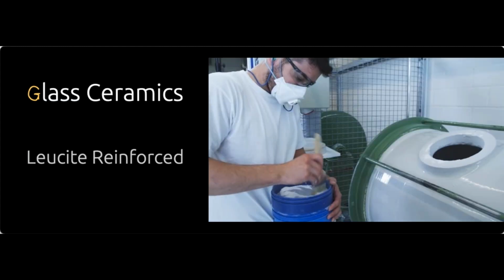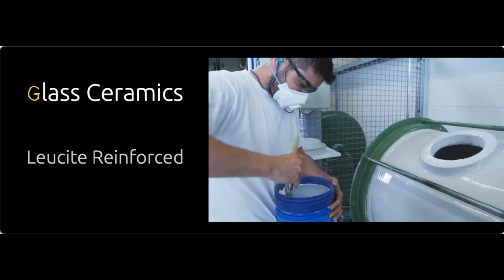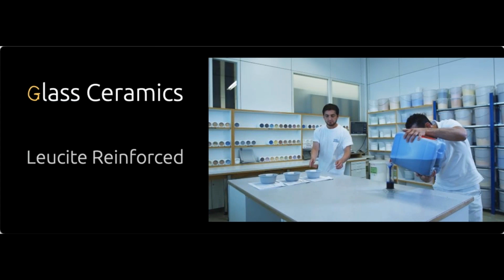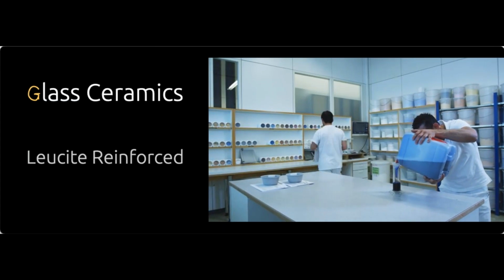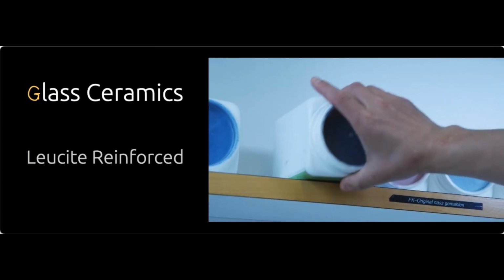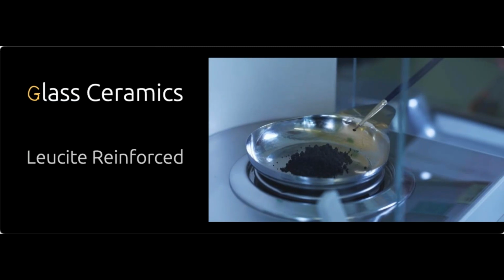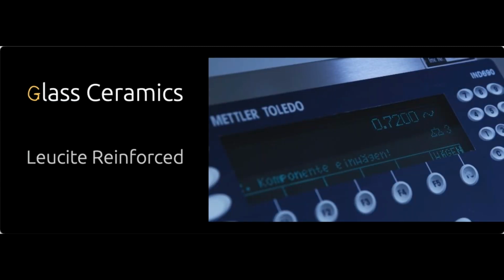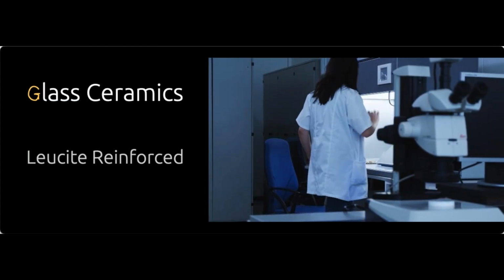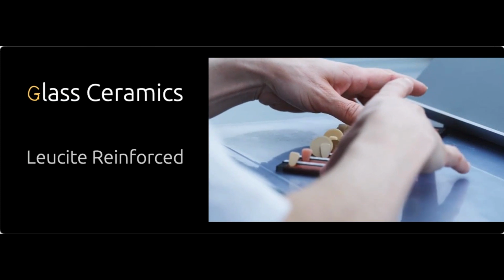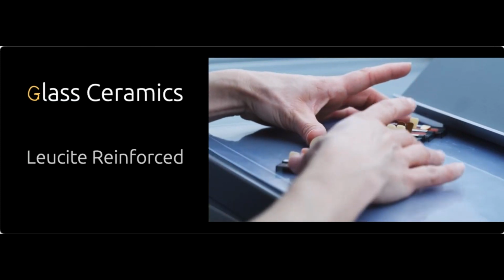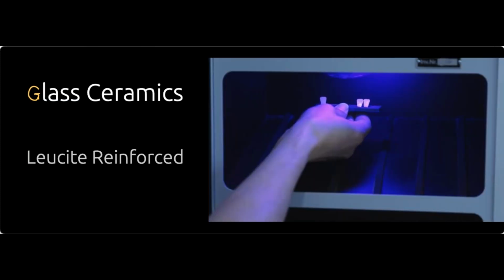However, the final result of what a glass ceramic is, a feldspathic crown, a Mark II or an Empress, is glass. So as you know how the plastics that we just talked about behave, you also know how the glass behaves. What are the good things about glass? They're beautiful. Glass is beautiful. We can stack porcelain on it. We can make intricate things to come from the inside, so it looks beautiful. They're translucent, they're fluorescent, they don't wear as much, they don't change shape over time as much as the composite because of wear.